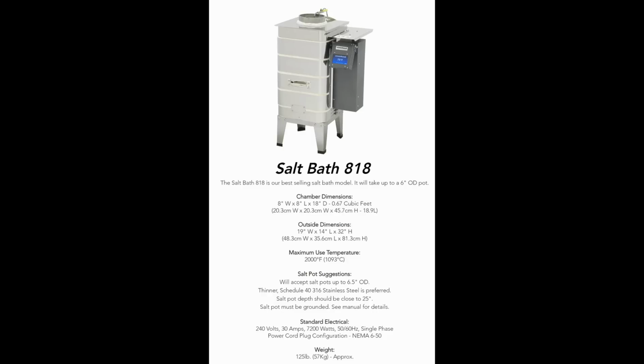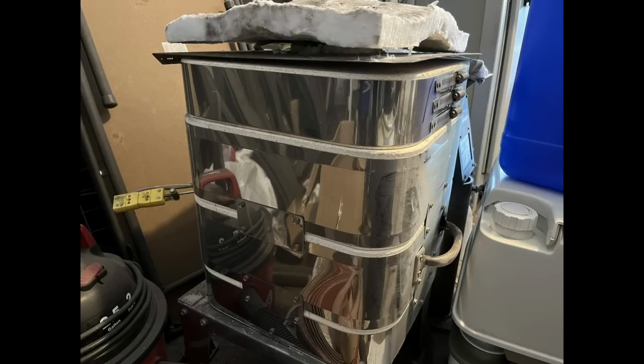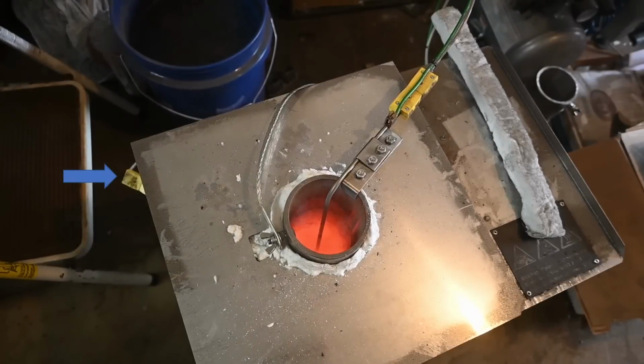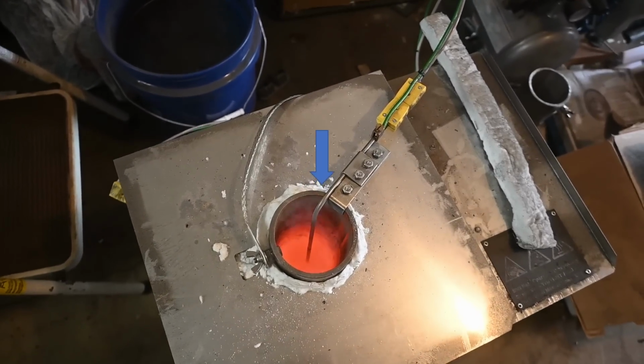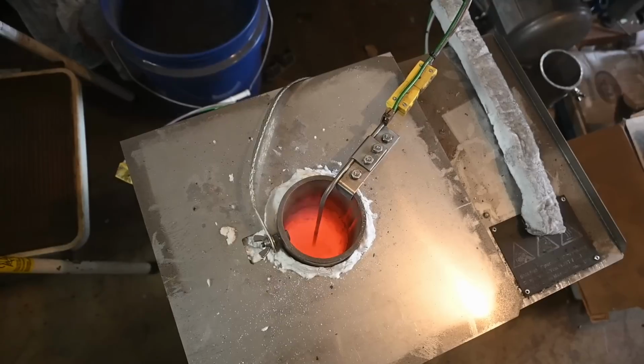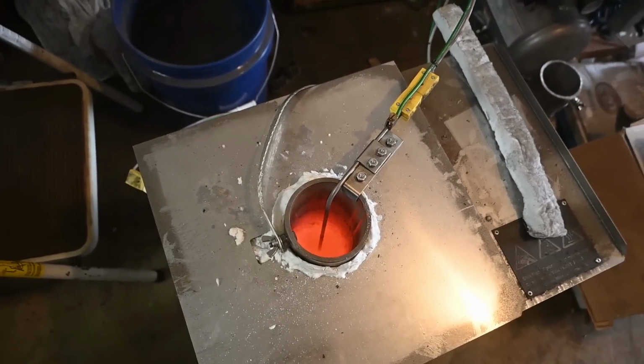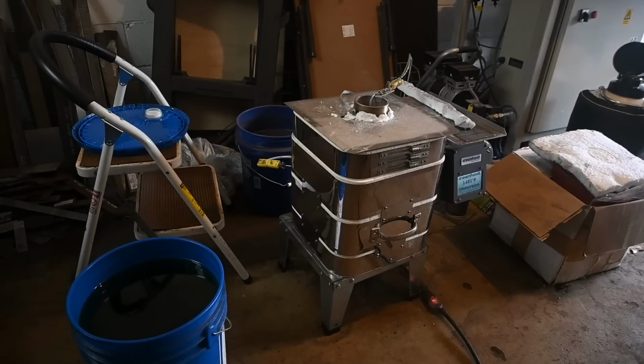Though when you operate the furnace, first you heat to your target temperature using the thermocouple inside the furnace itself. Then, once the salt melts, you switch over to the secondary thermocouple, you stick it into the molten salt, and then you change the mode so that it's running off of the salt bath thermocouple instead. So that's how you operate it. It's not that complicated, though we should probably talk about salt pot safety for a second.